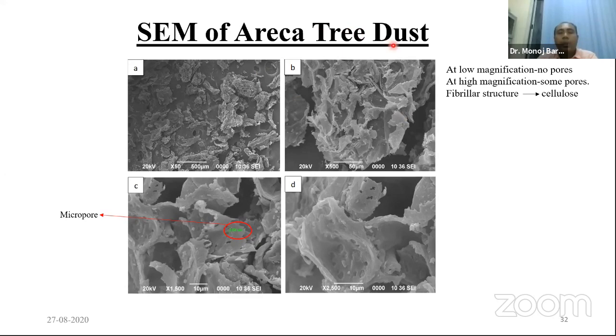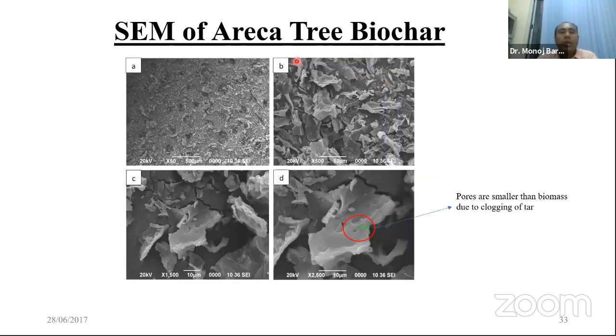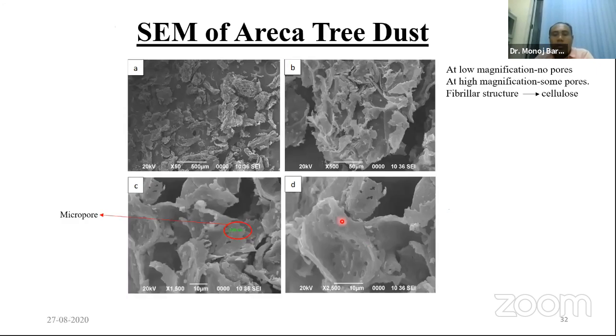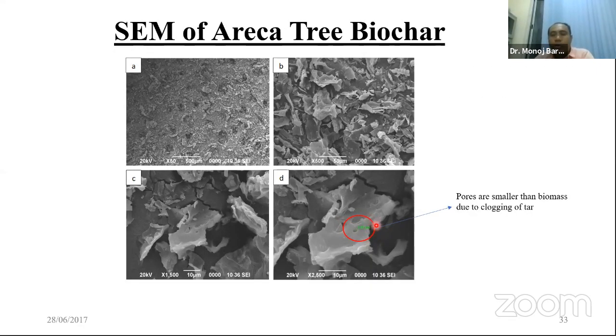Now this is for the biomass. Now if we see its product, this is the solid product of this Areca tree dust biomass, that is the biochar. Here also we can see different magnifications, from lower magnification 50 times up to 2,500 times. At lower magnification, no significant features were observed, but at the higher magnification, we can see that some very small pores are found. It's about 1.87 micrometer. So if we compare the size of micropores between the biomass and the biochar, the size of the micropores has reduced. This is because of the process of pyrolysis, because in pyrolysis, due to tar production and the clogging of this tar, sometimes the size of the pores may reduce.